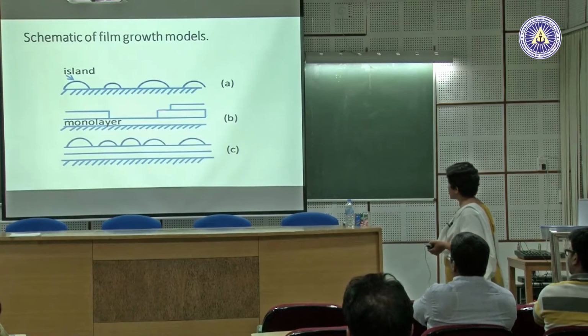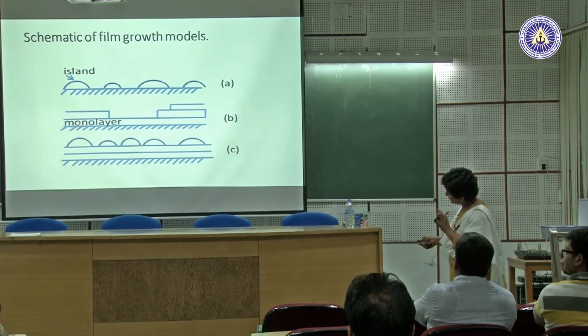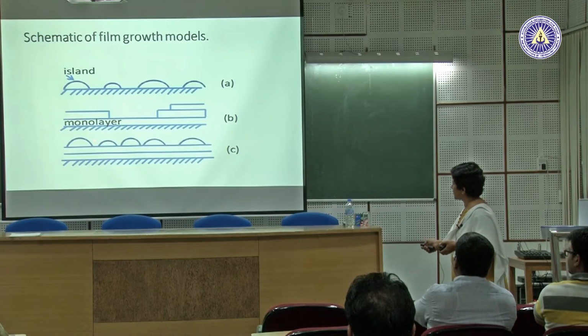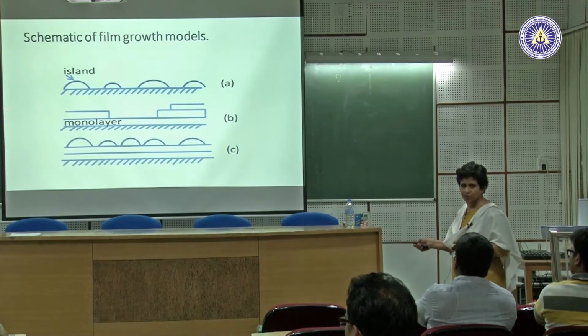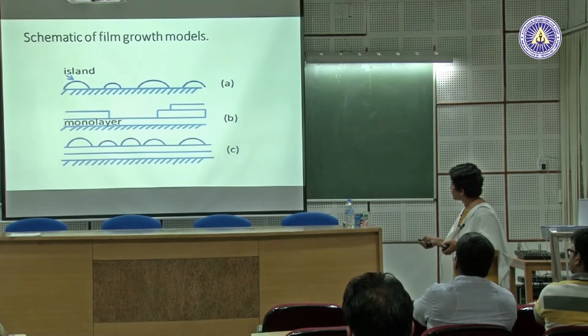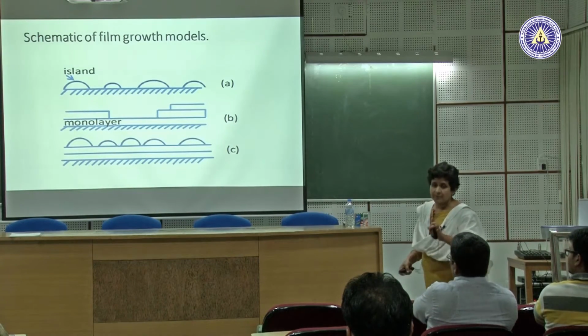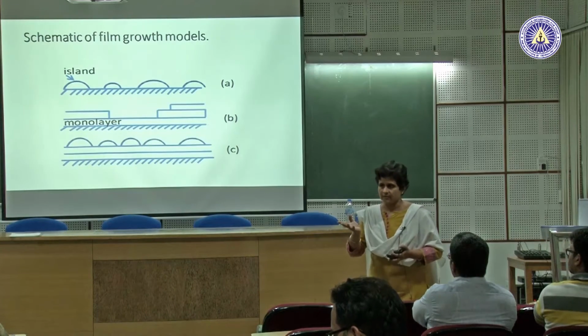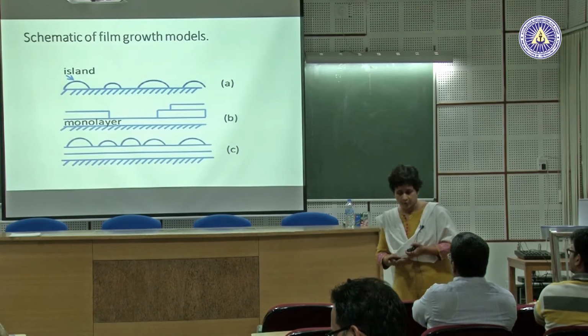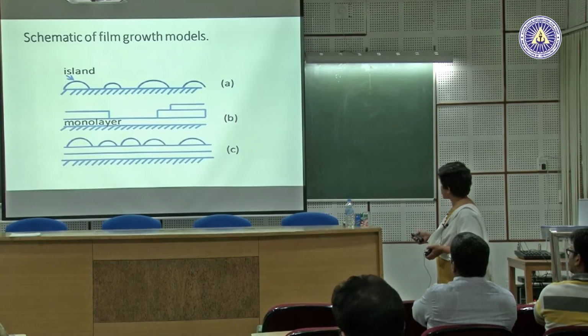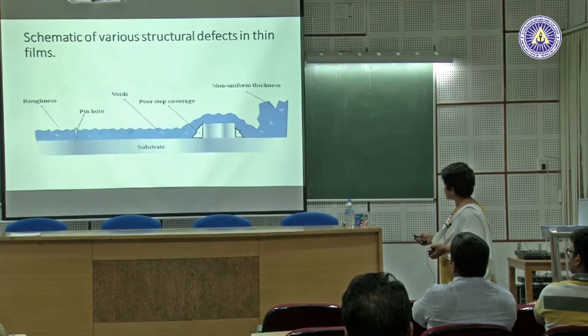Then depending on if your material and film properties match, you can actually have nice uniform films. And these are areas where you also control the parameters for deposition. You can have epitaxial films, meaning single crystal films. Silicon single crystal films are also grown. And then sometimes you can have a combination of the two.